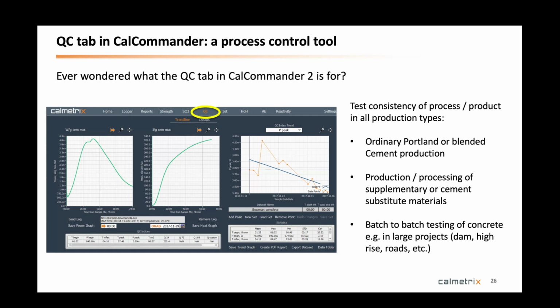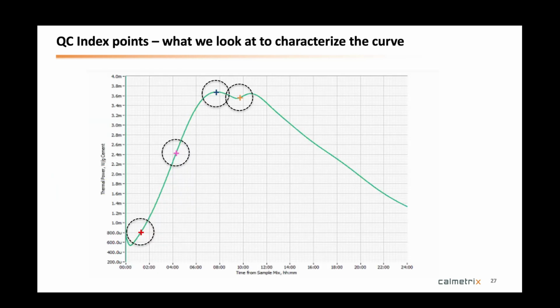And the way we look at this, we try to characterize the curve by a few points on it. And based on our experience, because we're all guys that come from this world of cement and concrete, we have defined a few of those points. So there's nothing universal about those. There's nothing that comes from a norm or a standard. It's still an open book. So if anybody, for example, in this crowd of people today, were to come up with something that's a good idea or better, that can always be added. But for now, we have a few points there. I'll show you what they are. And these are the ones where we look for consistency on those points from one curve to the next.